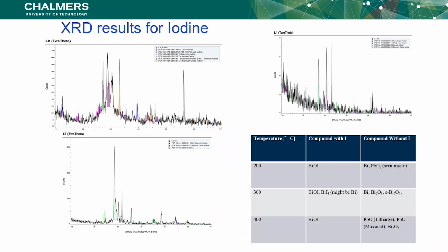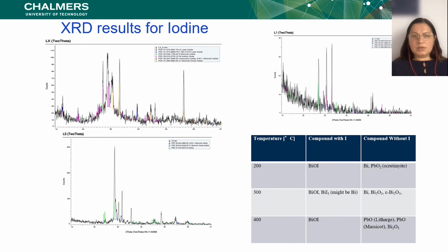then we could collect the samples and we analyzed with XRD the results for iodine, and we found out that we have a lot of compounds forming depending on the temperature, which is also very good to know. So when you make a calculation for safety reasons, you have to know what phases are forming at different temperatures and also different compounds. Next, please.